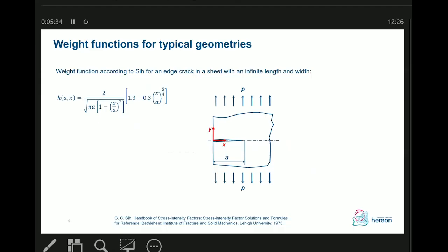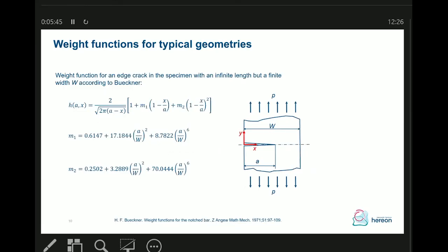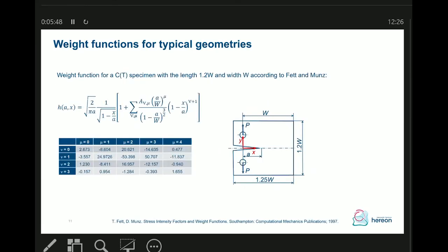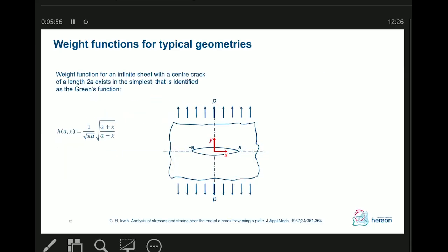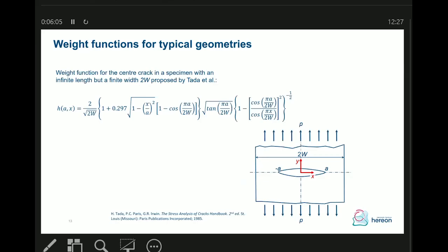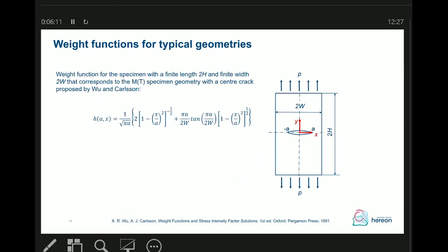There are some solutions, for example, for an edge crack with infinite length, where we can use the solution according to Sih. For a specimen with infinite width, we can use another, and here for a CT50 specimen, for example, according to Fett and Munz. And for a central crack, we can use, for example, a simple Green's function. If we consider the finite width, we can use the solution according to Tada and others. And for the MT specimen, a solution exists from Wu and Carlsson.